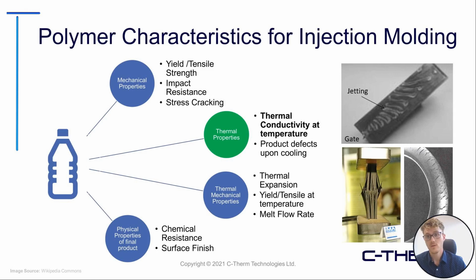So some of these defects include jetting, where cooling of the polymer or mixing of the polymer during the injection leads to streaking and undesirable characteristics. Additionally, welding type of defects where polymers are meeting together and not quite molding completely. This can lead to delamination or stress cracks, blistering, or burning of your final product, which are all undesirable characteristics.